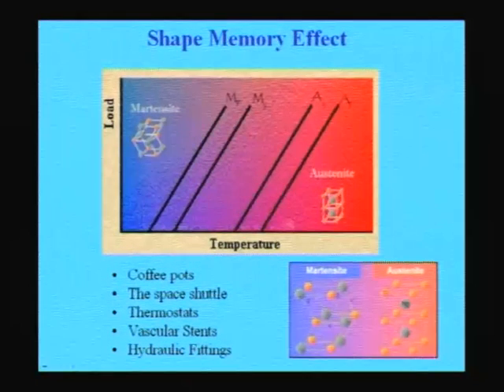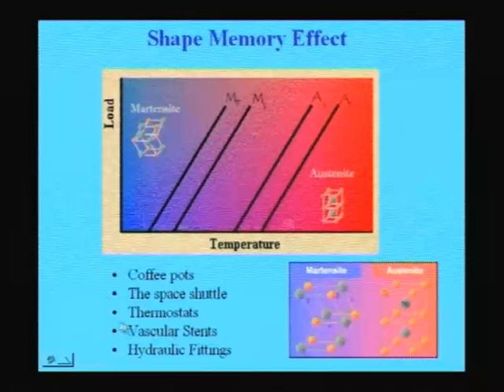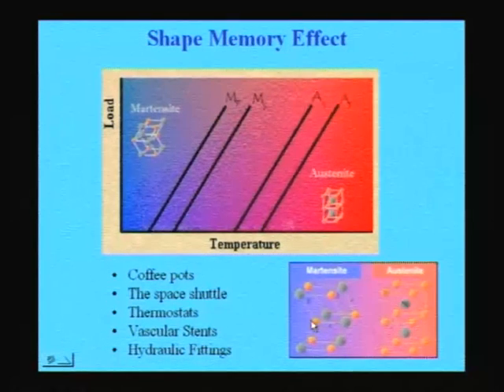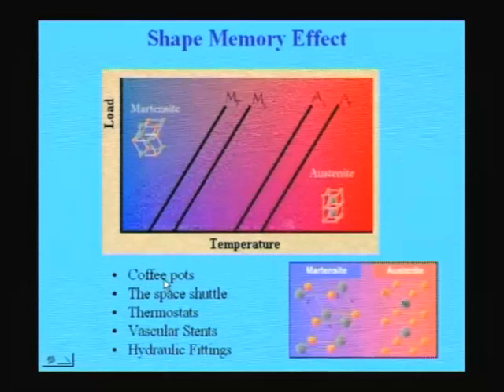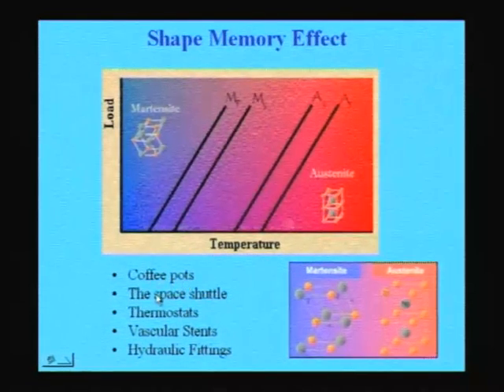So the basic structure is shown here. You can see it is the cubic B2 type of structure, titanium occupying all the body corners, nickel occupying the body center. That is a typical austenitic structure, B2 type, and when you change it to martensite, it becomes rhombohedral. This is the typical rhombohedral type of structure where you have the atoms occupying again similar positions, but the structure changes from the BCC type to the rhombohedral type. A number of applications are given here where we use the shape memory effect, starting from simple coffee pots to a space shuttle, thermostats and hydraulic fittings, different applications where we use this shape memory effect.